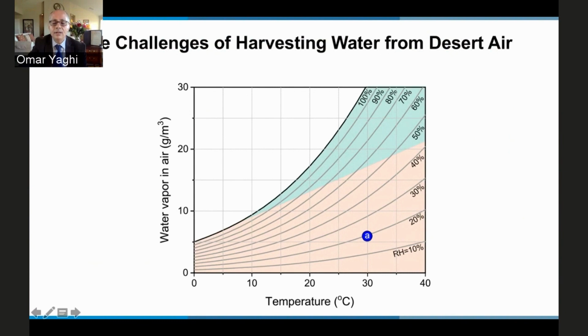So I have a relative humidity of 20% at 30 degrees Celsius. In order for me to use the cooling cycle, let's say to get water out of that air, I have to cool down that air to 4 degrees Celsius. Well, that's energy intensive. That's like refrigeration. So that's not a viable way of harvesting water from air.